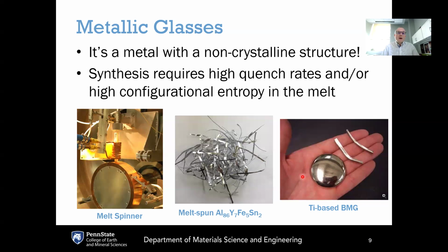And the mechanical response of most metals is characterized by their crystalline defects. If you've got dislocations in metals, those dislocations can move in response to mechanical stresses. Grains can move against each other. You can have grain boundary sliding. And what this means is that metals can dissipate energy because of these defects in the crystalline structure.